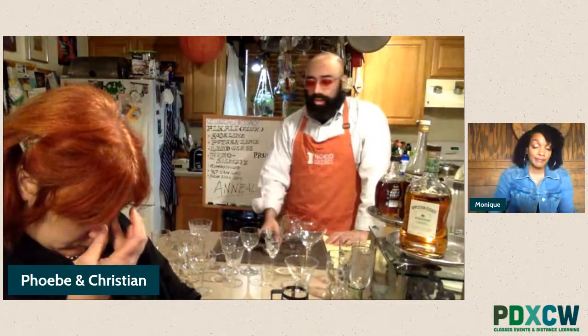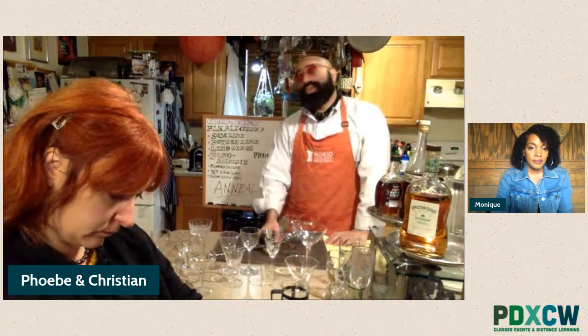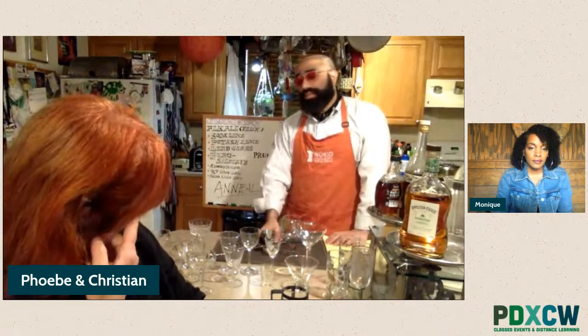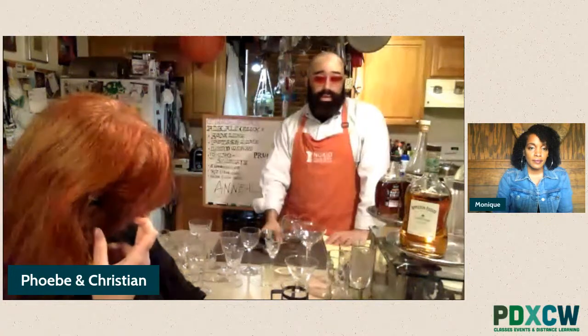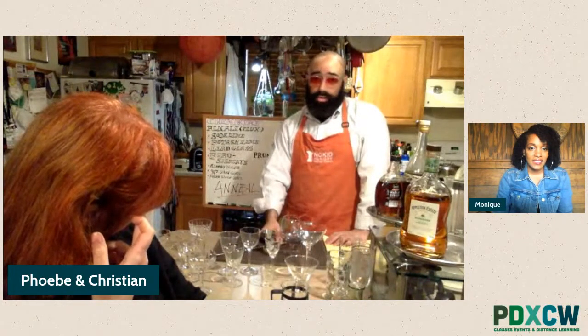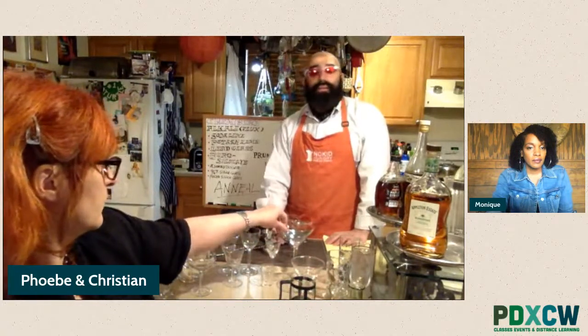Hand washing in general, or with a sponge, is actually probably good. The other reason you wouldn't necessarily want to put lead glass in one of those 3 sink baths is, unless you're one of those people who tends to let your water get cool so that your hands aren't uncomfortable, then maybe you can wash the lead glass in there. But if you've got a 3 sink bath that's hot enough in its first stage, as hot as you'd like it to be for cleaning, the thermal shock of sticking it in there could potentially crack a very finely rimmed glass. So that would be another consideration. The companies recommend that you wash crystal in warm water, not really hot water.